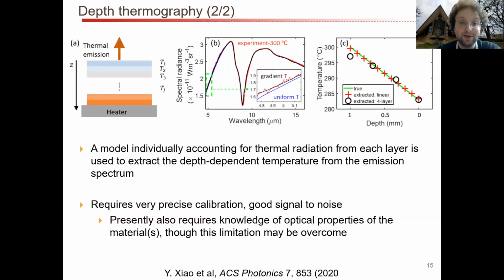And because we're able to do that, we're then able to say, okay, given this spectrum, without any information about the temperature, what is the temperature? And long story short, we are able to back out the temperature as a function of depth quite well, making certain assumptions. So right now, this requires very precise calibration, good signal to noise, both of which we have, but also it requires the knowledge of optical properties, which is potentially difficult, and you have to do some other measurements to be able to do that, though we think that this limitation can be overcome. And so again, I remind you to check out Yuzhe's talk to see more details about how this was done.